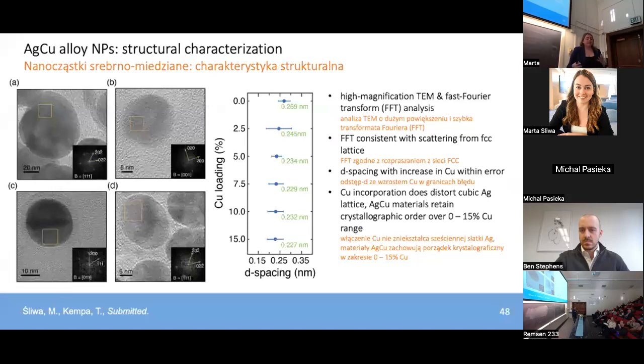We also see that lack of segregation with increasing amount of copper when we look at the structural effect of the increased copper in these silver copper alloy nanoparticles. So specifically, again, we were very interested in determining if, when we get to that 15% upper limit, do we see any phase segregation of the alloys into copper-rich or silver-rich components, or do we still have that uniform distribution?